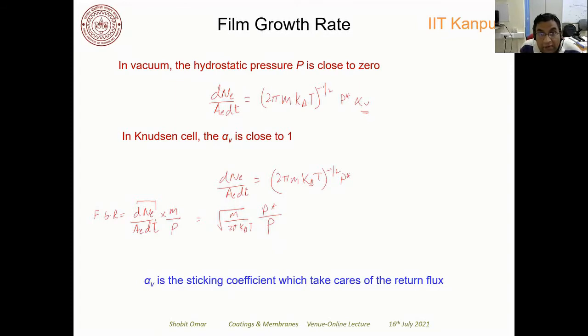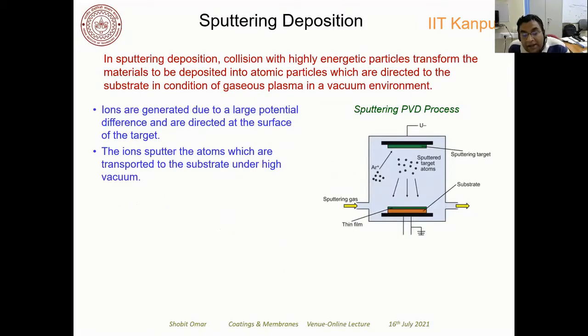So let's talk about the sputtering deposition technique, which is another type of technique which people use, and it's very common when you are depositing a noble metal, right? In this sputtering technique, you use plasma, highly energetic particles, to sputter the target surface, and these atoms in the gaseous form start getting deposited as a thin film on the substrate. So what you do is basically ions are generated due to large potential differences and are directed at the surface of the target.